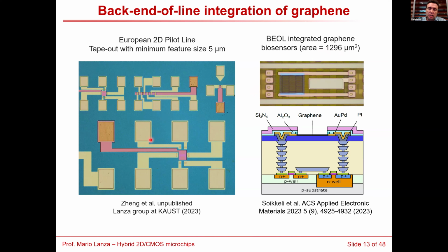This image is from a microchip that we designed in the 2D pilot line from the European government, in which we can fabricate some graphene field effect transistors. This is also using graphene transfer on top, and then you can pattern. And the minimum feature size that can be patterned is 5 micrometers. So this is also not very high integration density, although here we managed to make different kinds of transistors.